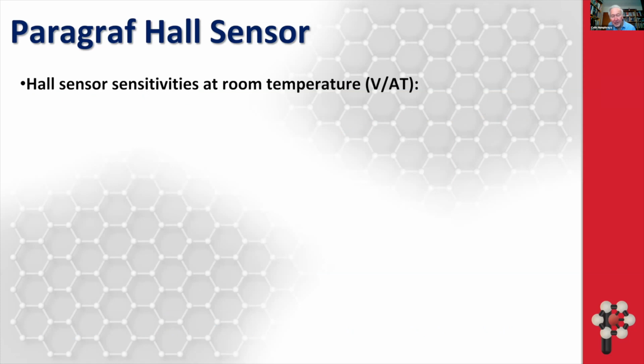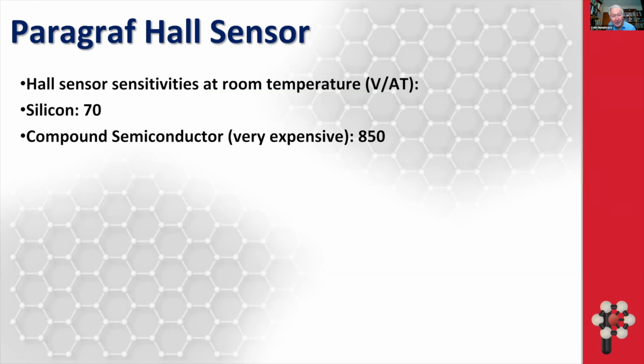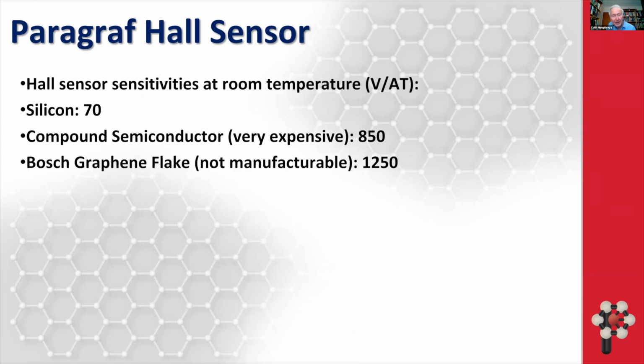And so these now give you the sensitivity of the Hall sensors you can go and buy. The silicon Hall sensor is 70 volts per amp Tesla. Compound semiconductors like gallium arsenide are better. They're also very expensive, 850 volts per amp Tesla. The Bosch graphene flake, if you look at their paper, which was assembled by hand, not manufacturable, is over 1,250 volts per amp Tesla.